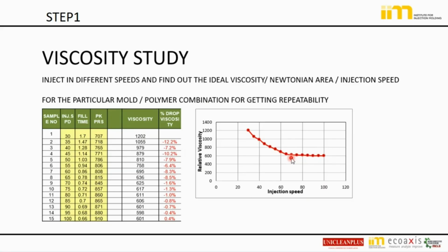So this is what we first have to find out, and we have to keep somewhere. Most people prefer to keep in the bending area, but personally, if you are very good at tooling and know how to correct things, if you know what the reason is, I personally tell you that you can shift a little more ahead and keep it, to get the utmost consistency in terms of dimension. If you are operating in this sliding area, where it is non-Newtonian polymer, and every change in the shear or raw material property changes the viscosity, forget about consistency. So this is the sweet spot we have to identify in viscosity studies.